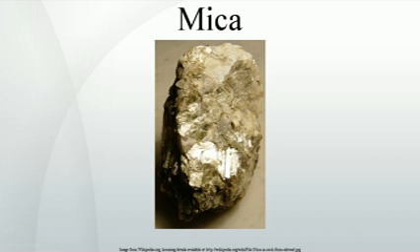Mica is stable when exposed to electricity, light, moisture, and extreme temperatures. It has superior electrical properties as an insulator and as a dielectric, and can support an electrostatic field while dissipating minimal energy in the form of heat. It can be split very thin, 0.025 to 0.125 mm or thinner, while maintaining its electrical properties, has a high dielectric breakdown, is thermally stable to 500 °C, and is resistant to corona discharge.